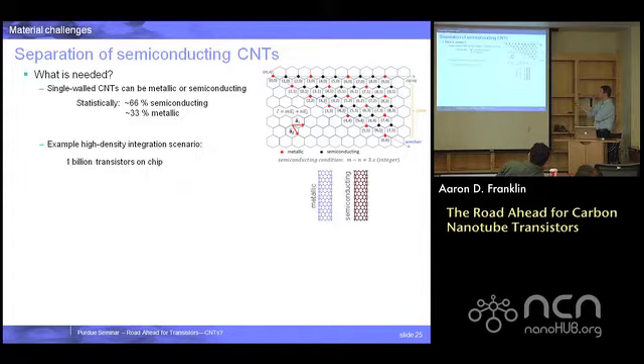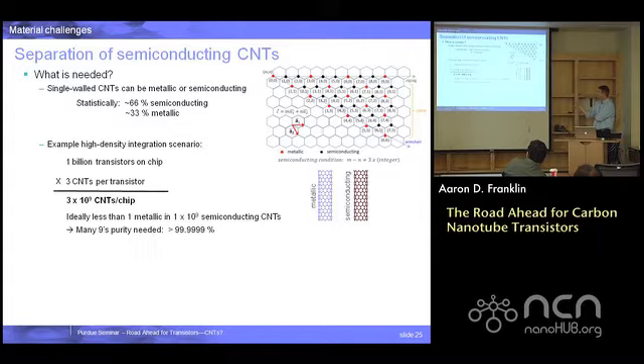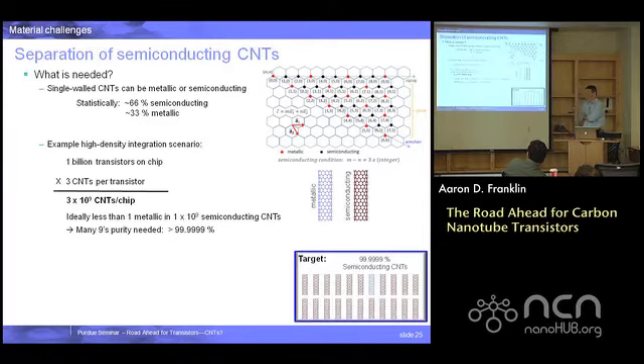Well, first, if you look at what is needed, if I have a chip with, just as a back of the envelope, 1 billion transistors and 3 nanotubes per device, because you're going to need more than one in each device to get enough current out of it to drive things on the chip, then that's about 3 billion CNTs on the chip, which means I need a purity of about 6 nines, percent semiconducting nanotubes out of this. That's pretty daunting. Right?